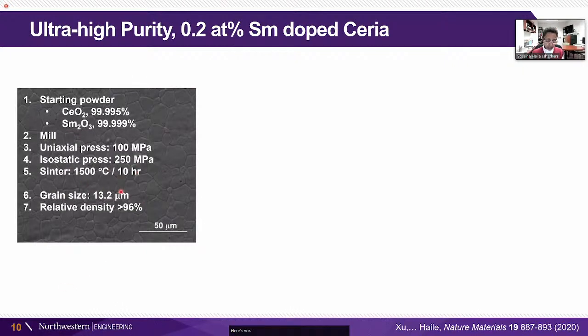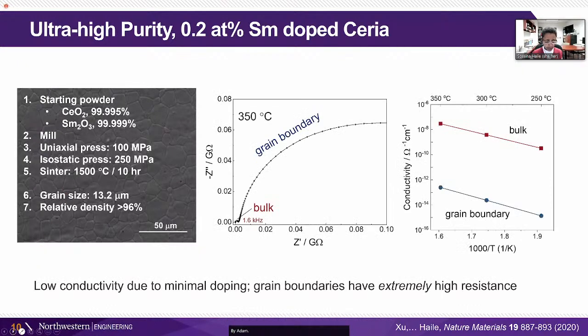Here's a very typical material that we've started off with. As I said, very, very lightly doped, so 0.2%. And we sintered this so it has large grains so that we can access any one of these individual interfaces. And we're going to do that then by electron holography and by atom probe tomography, actually.